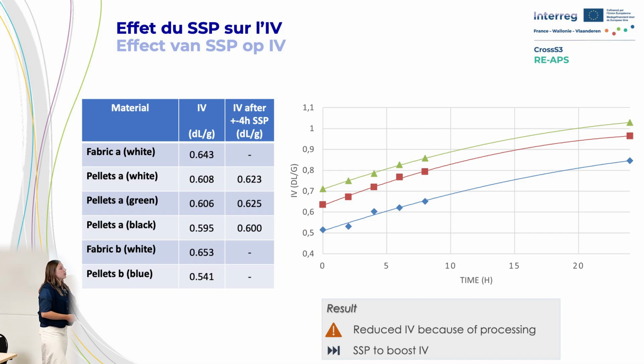Also, we did some other IV and SSP tests on other materials, and we see that for a range of initial values we were able to increase the IV with SSP treatment, and by a longer duration of the SSP, the IV increased. So that's a nice result, and it's also a good practical guideline to estimate the required duration of SSP for our materials.